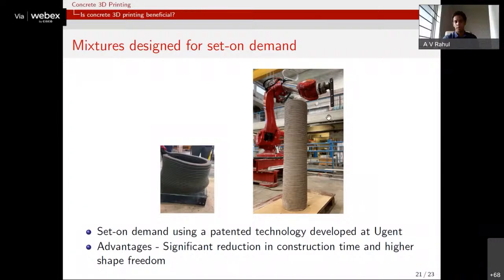But on the right hand side, here we work on a technique called set on demand, where an accelerator is introduced just at the nozzle, which significantly alters the stiffening rate of the concrete. So the introduction of this accelerator causes it to undergo a flash set. And this allows us to make much larger structures. So here, this column is about 1.5 meters, and it's showing no signs of failure until now. And this was made at a very rapid construction speed. In fact, this was printed 4 times faster as compared to the first element. So the higher rate that you can achieve, and also the higher height that you can achieve with this technology, is one advantage with the set on demand type approach.